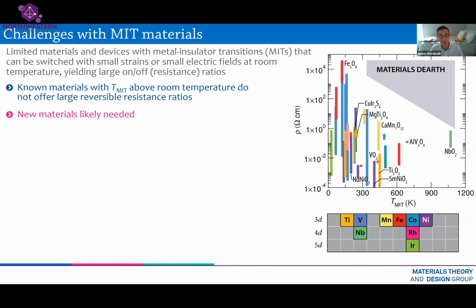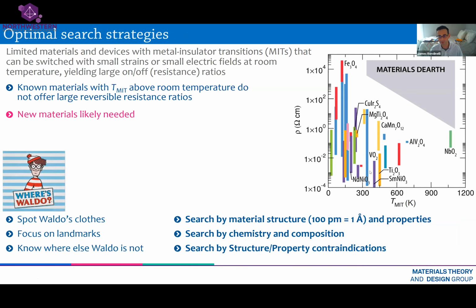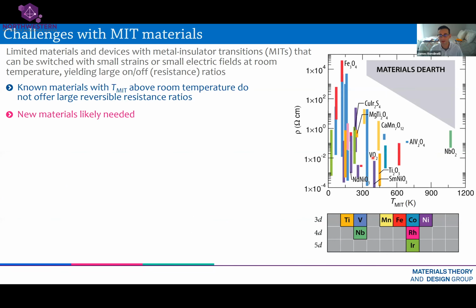So things like vanadium dioxide, which I already mentioned to you. So this is the temperature at which that thermal transition from the metallic to insulating state would occur. So it's somewhere around 350, oops, let me go back, 350 for vanadium dioxide. For this material, niobium dioxide, which adopts the same structure, it's much, much higher temperature. And then the width of this bar tells you how large the change between the metallic state and the insulating state is. And really, for these types of devices, what we want are materials that operate at least around 100 C, so somewhere up here. And this resistivity ratio is very large, like 10 decades or 5 decades would be good. So something like a bit larger than what vanadium dioxide is.